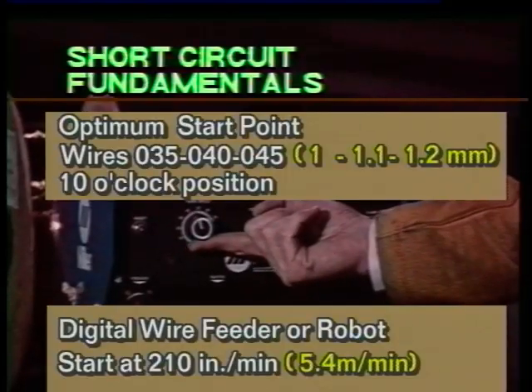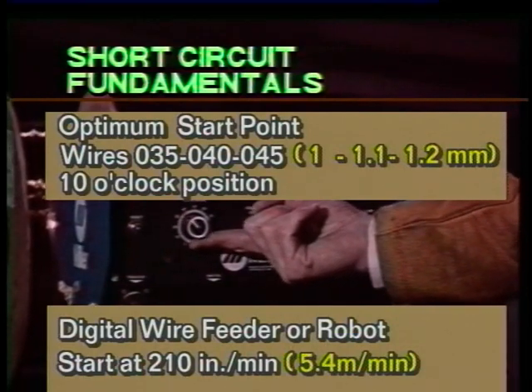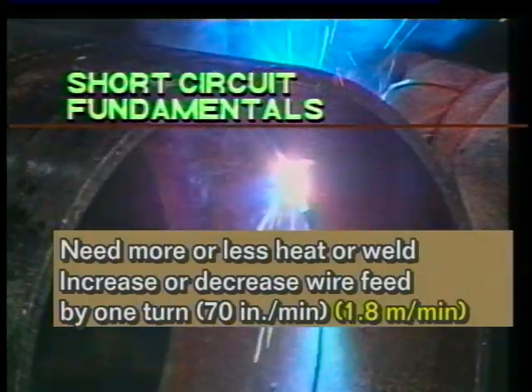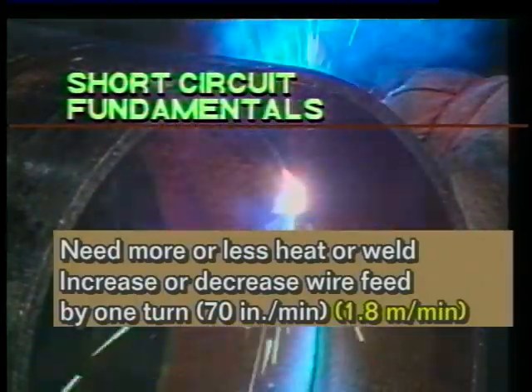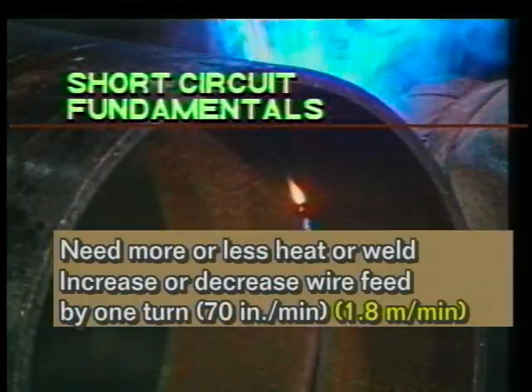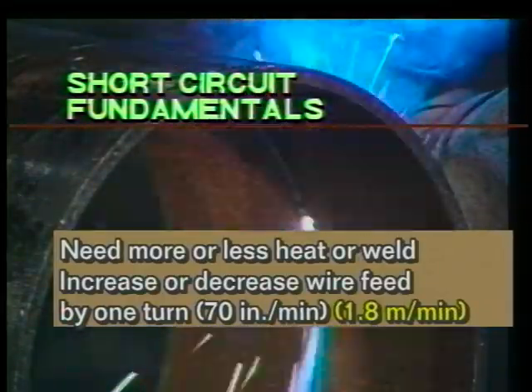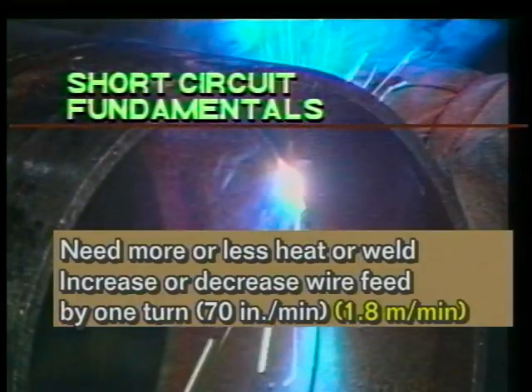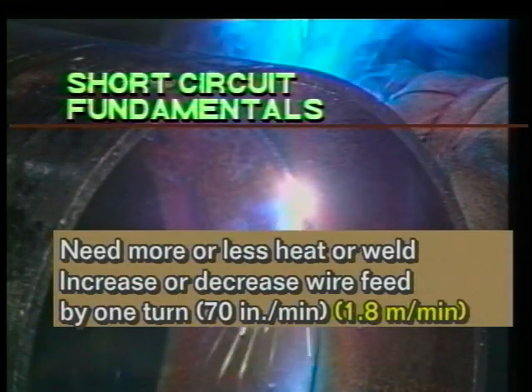When welding thin gauge carbon steels or stainless, start out at the easy to remember 10 o'clock position. If you need more or less heat or weld, increase or decrease the wire feed by one turn. Remember that 70 inches a minute or 1.8 meters per minute.